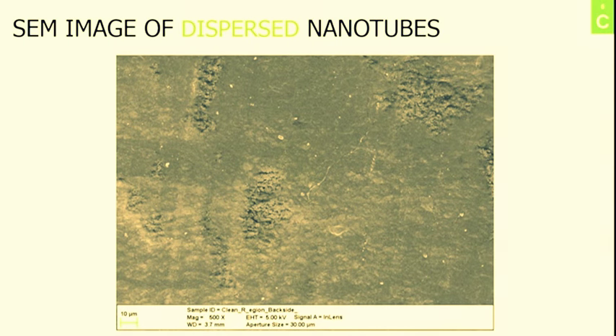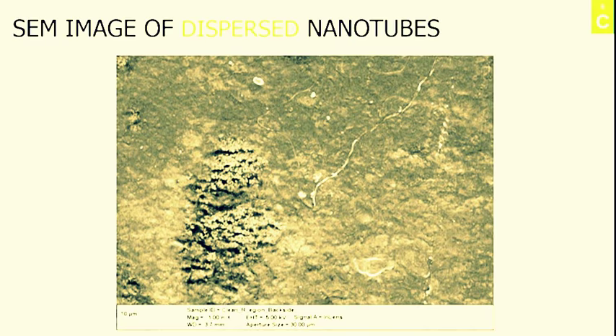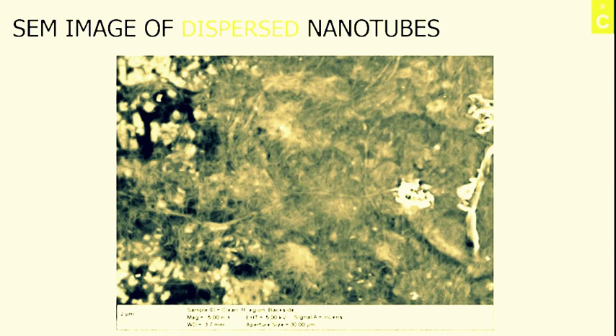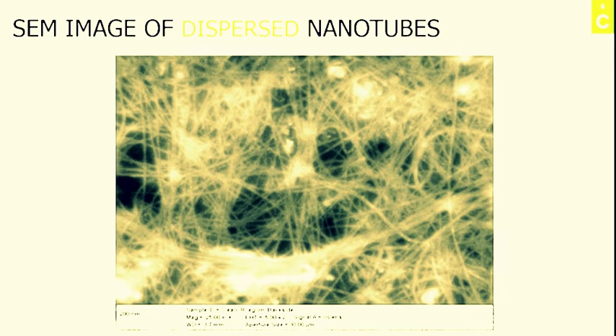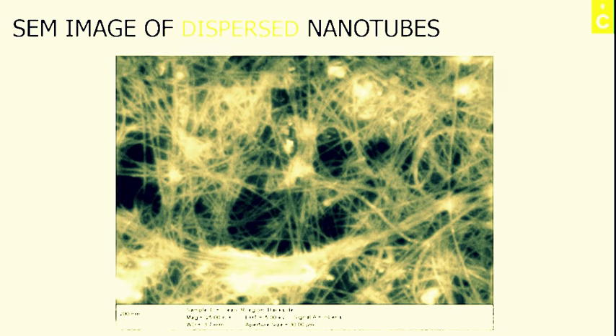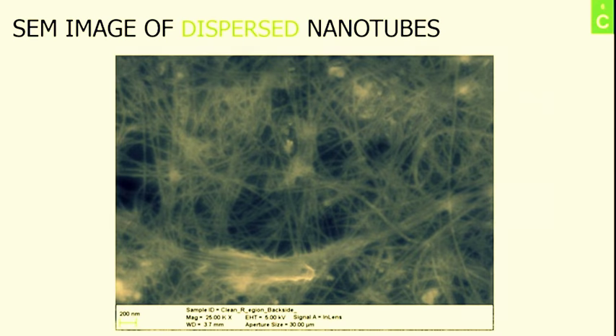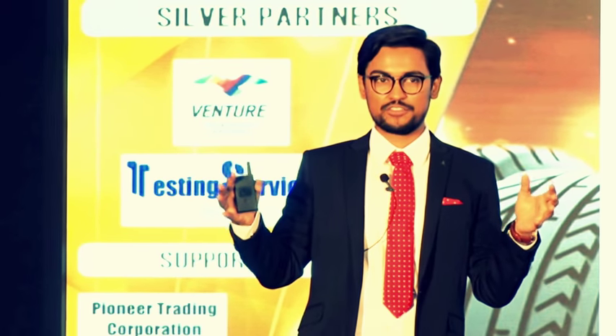So how do they look when they are dispersed properly? This is a SEM slide under various magnification. As I go deeper and deeper, you'd be able to see these fluorescent lines, which is a percolating network of single-wall carbon nanotube. So what essentially happens is, single-wall carbon nanotubes form their own 3D conductive network throughout the matrix of the polymer. And this provides you all the properties of single-wall carbon nanotube exhibited in your end polymer.